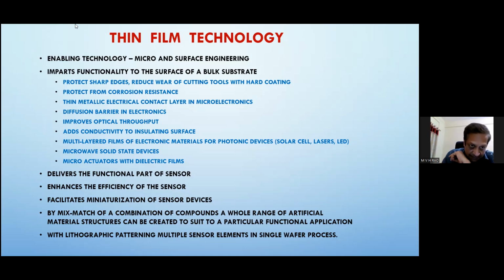So in the case of optics, using anti-reflection coatings, we can improve the optical throughput. This is an essential aspect. Without anti-reflection coating on the lenses, there will be no optics, because each surface will have a minimum of about 4% reflectance, and the combination is about 8% reflectance if we don't do ARC, and that will generate ghost images and all. So the picture won't be good. So we need to put anti-reflection coatings so that the reflection losses are minimized, to less than 1%. And then only the appropriate light throughput will be there and image quality will improve.